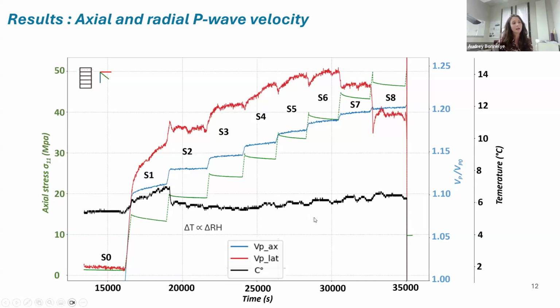Here in black, we can see the evolution of temperature, which is correlated to the relative humidity, because we are inside of the SEM. We can see in green the evolution of the axial stress with the relaxation steps, and in blue and red the evolution of velocity. All of that is taken as a function of time, and we can see variations of velocities together with the loading of our sample. It can seem a little bit weird, but we can discuss that later.